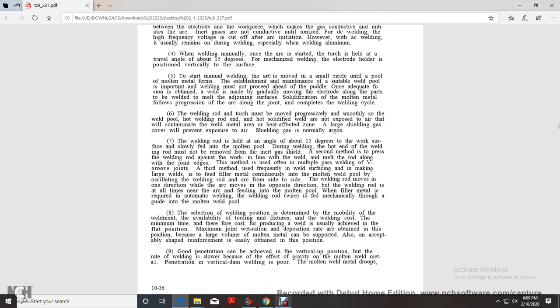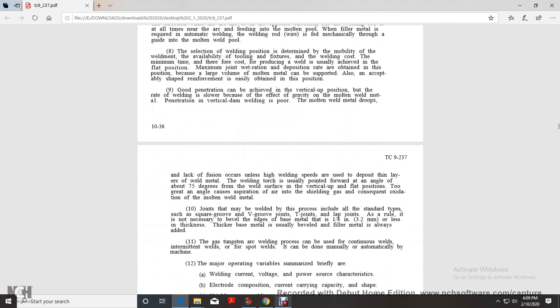Good penetration can be achieved with the vertical up position, but the rate of welding is slower because of the effect of gravity on the molten weld pool. Penetration in vertical down welding is poor, with molten metal drops and lack of fusion, unless high welding speeds are used, usually depositing a thin layer of weld metal. The welding torch is usually pointed forward at an angle of 75 degrees to the welding surface in the flat position. A greater angle causes aspiration of air into the shielding gas, and consequently oxidation of the molten and weld metal.